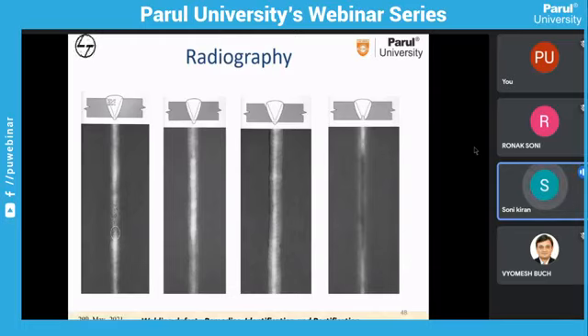So if any defect is there, let's take the example of the last image, there is suckback, or I can say lack of penetration. Here is a suckback. Because of that suckback, at that particular location the density is very low compared to the weld metal. So there is a dark line for the base metal, and in the center a bright line for the weld metal, but where the suckback is, the radiation passes through that defect region and ionizes the film more. So the film becomes darker. This is how we interpret and detect that defect.